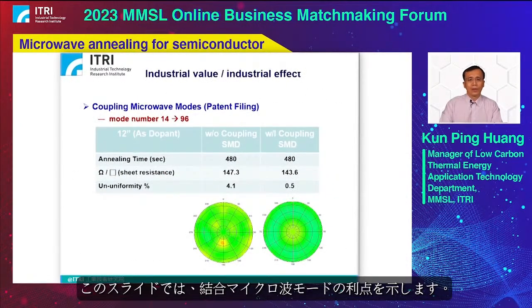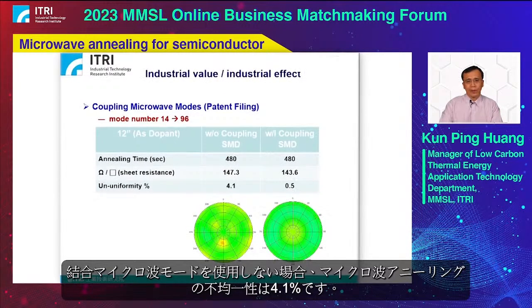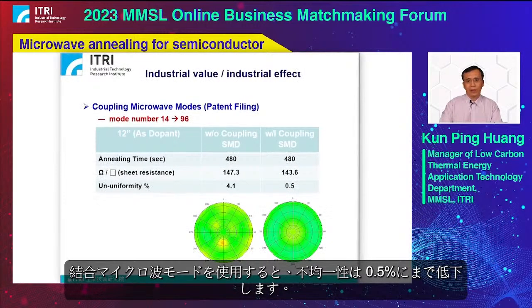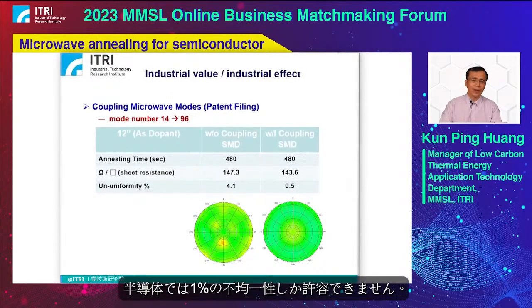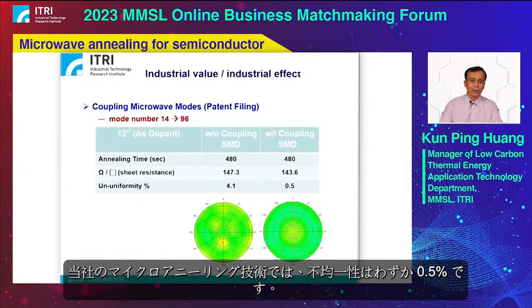Okay. This slide shows the advantage of the coupling microwave mode. If we do not use the coupling microwave mode, the uniformity of microwave annealing is only 4.1%. But if we use the coupling microwave modes, the non-uniformity goes down to 0.5%. In semiconductor, we can only accept 1%. So in our microwave annealing technology, the uniformity is 0.5%.